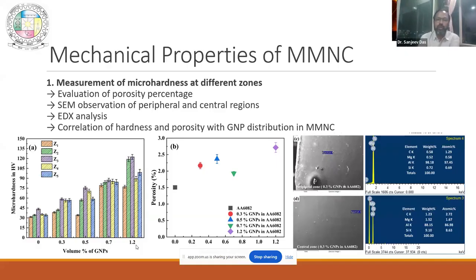which is basically increasing the hardness at the center. Now we have also checked the porosity. When we see the porosity, we find that in the composite, the porosity is relatively higher compared to the alloy. Now I have told you that there is no vortex formation, nothing can go from the top, no air entrapment is possible, but still there is some percentage, 2.5% in casting, which is not that much for a composite, but still some amount is there. That is because when we are making the pellets of these nanocomposites, we are not able to get rid of the porosity there. Those porosities are basically contributing in the final casting. So presently we are working on how to add these nanoparticles without having enough porosity in it.